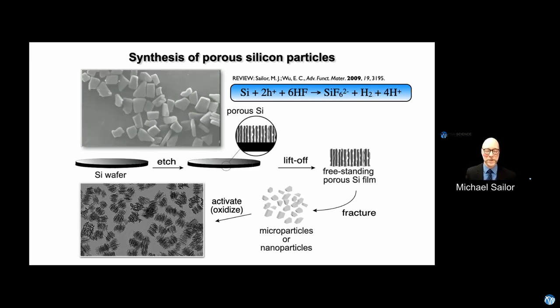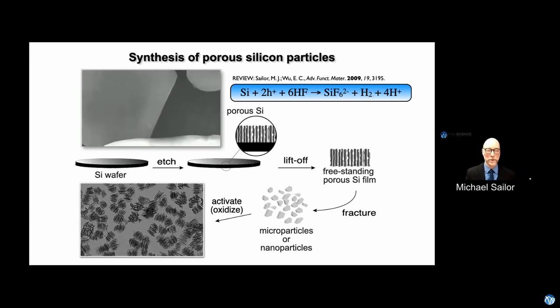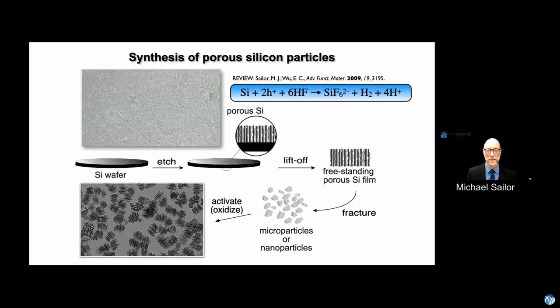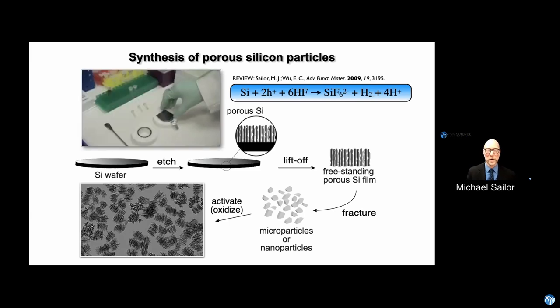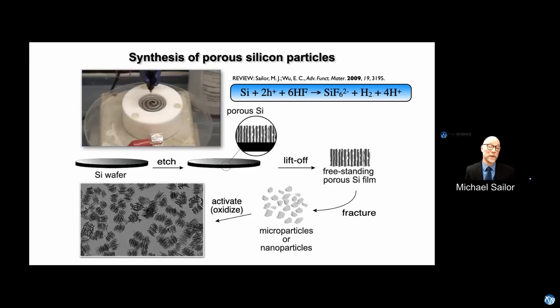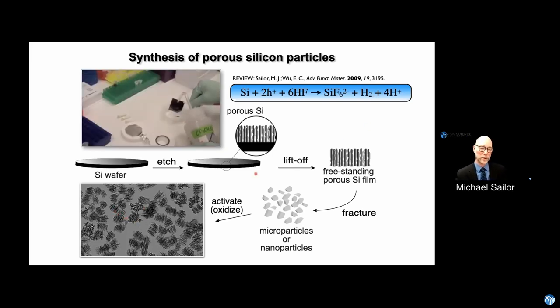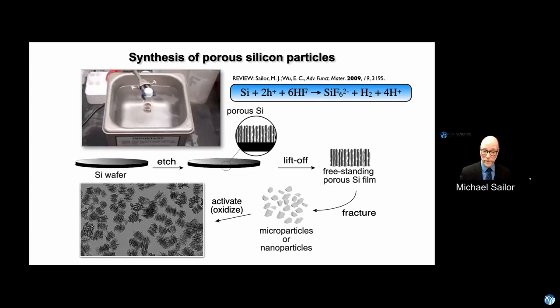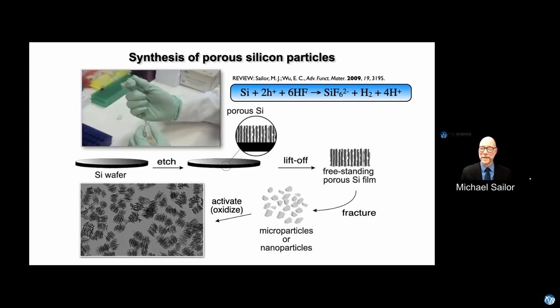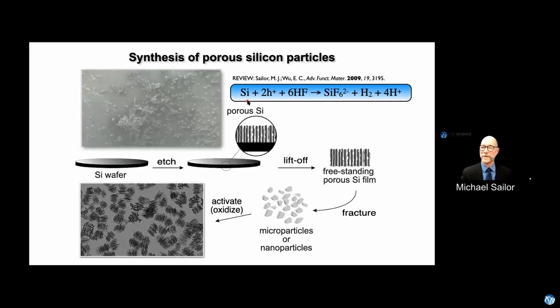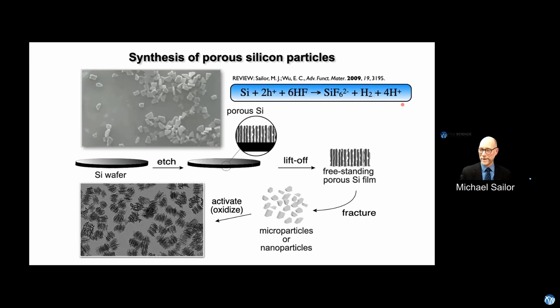The zoom here is just to show you that even though they look like big chunks of particle, if you get in really close, the pore size in here is very, very small. So these are basically nanoscale structures that can hold molecules or other payloads. A TEM image, a transmission electron microscope image, is shown on the bottom left. It shows what we have when we're done making our nanoparticles. It's made out of silicon, so it's basically a silicon skeleton. The electrochemical equation is shown up here. We can go into details on that later.